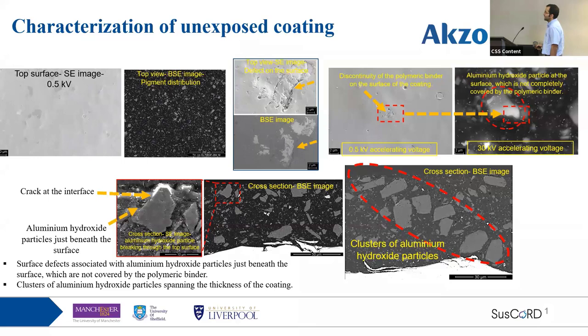But if we zoom in and look at the finer details, we can see that in the backscattered electron image there is a change of contrast, which could indicate a change in the material and atomic number. We associate this with pigments that are underneath the coating and are breaking through the surface. As you can see here, there is a heterogeneity, and if we increase the accelerating voltage, we can see exactly underneath this there is a pigment. This is a similar thing, but from the cross sections. You can also see there is a crack at the edge of these surface-breaking particles that may allow the environment to move in, at least up to this point, if we assume there is no further damage done. I have also seen clusters of aluminium hydroxide formation within these coatings, and this could also affect the performance, which we will talk about later.